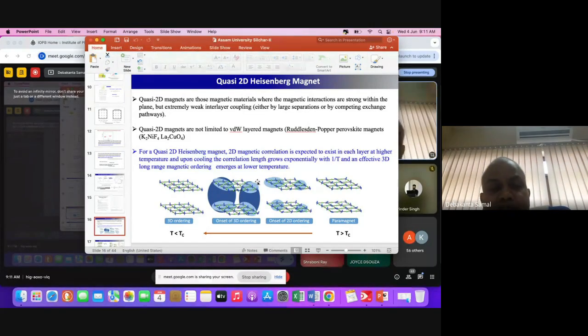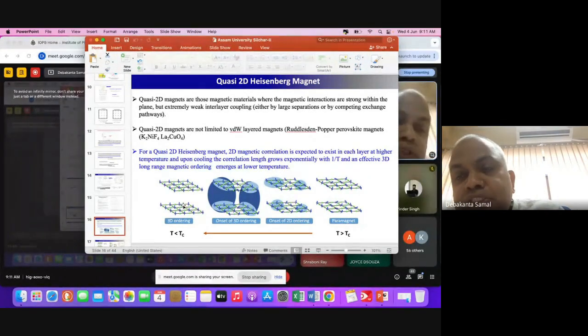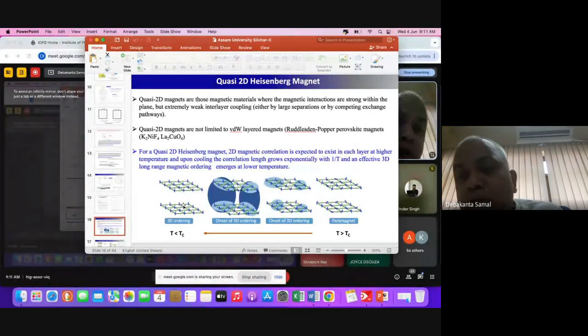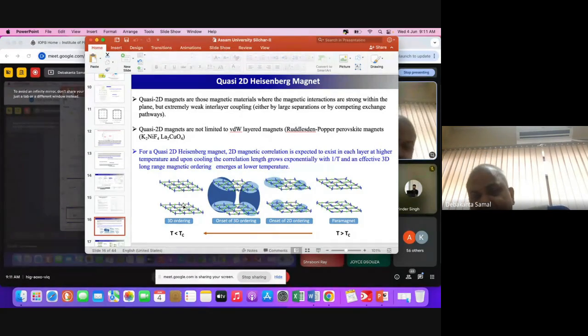One layer is magnetically active, another layer is magnetically active, but the separation between the two layers is very large. So the one spin in one layer and the other spin in the other layer couple with each other, but they couple very weakly, because the exchange interaction gets weakened with the separation. The more the separation, the more the exchange interaction gets reduced. That is what we know. The exchange interaction comes from the orbital overlap.